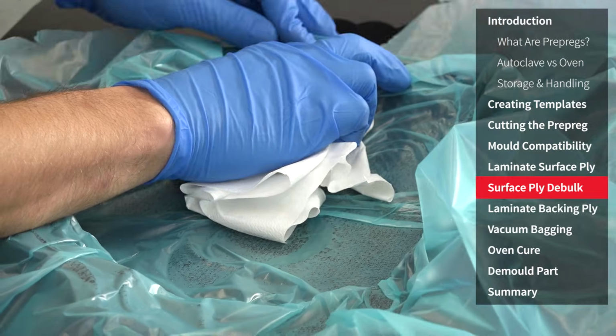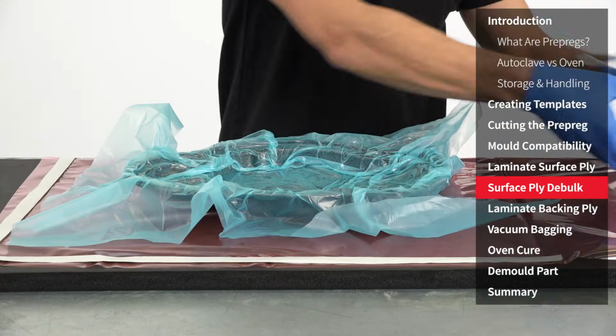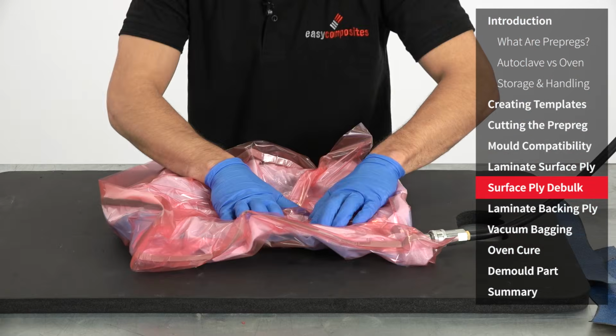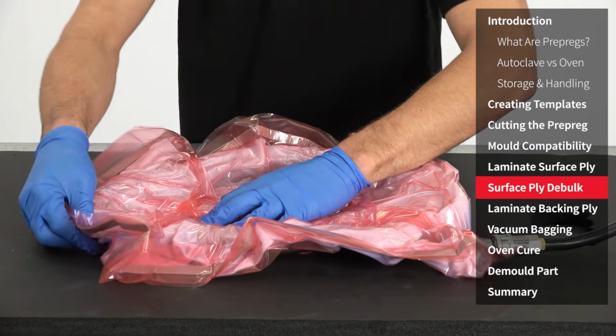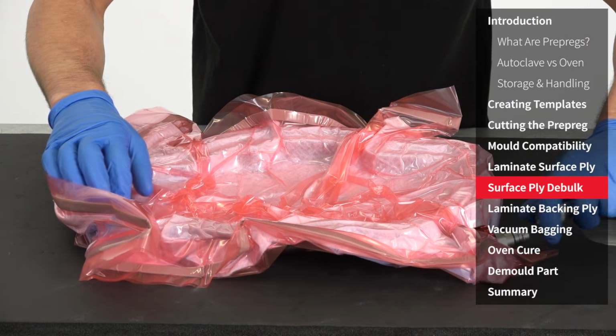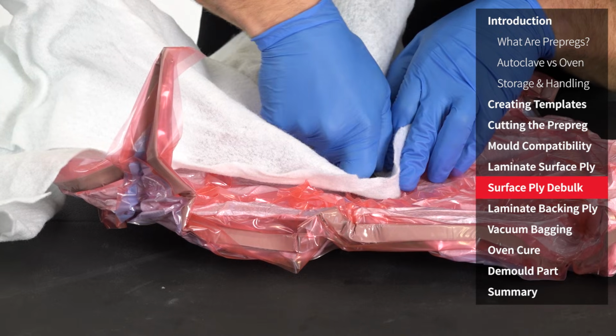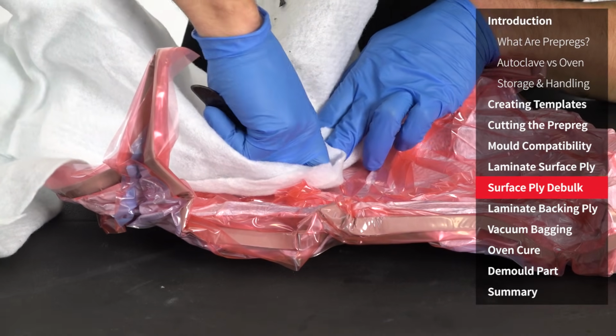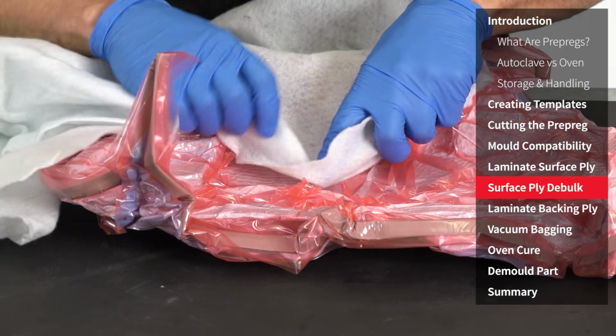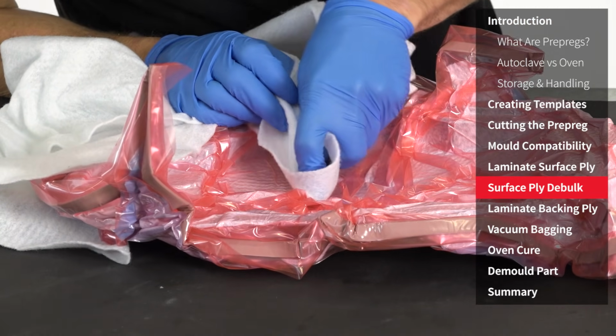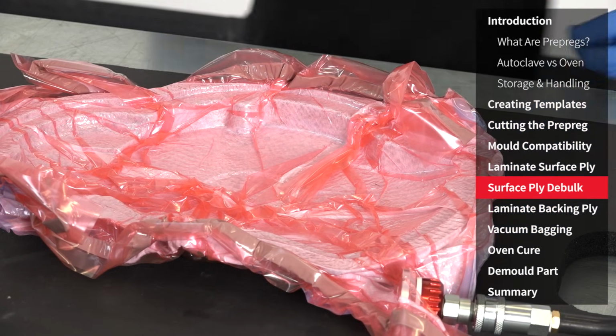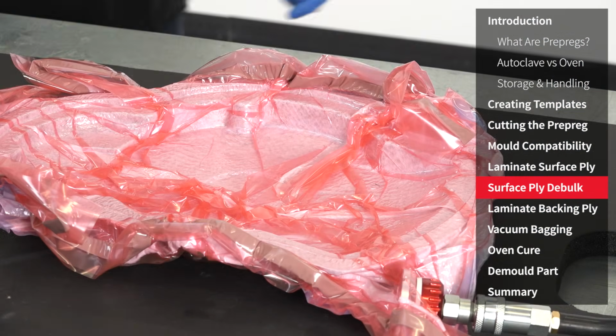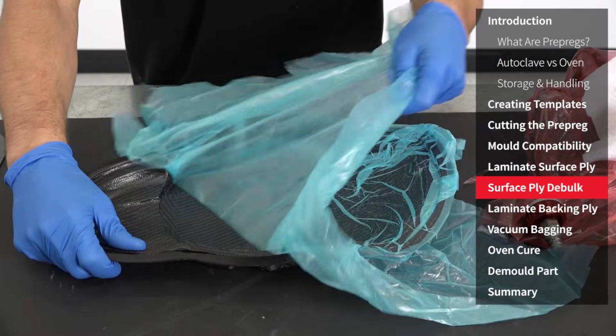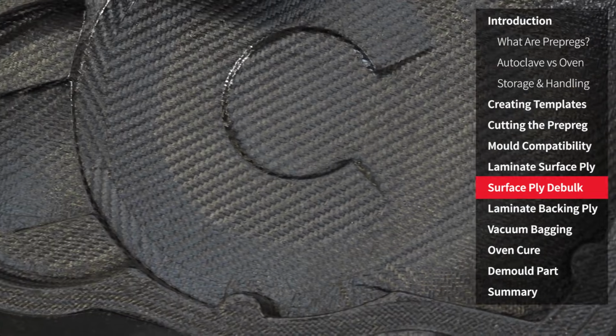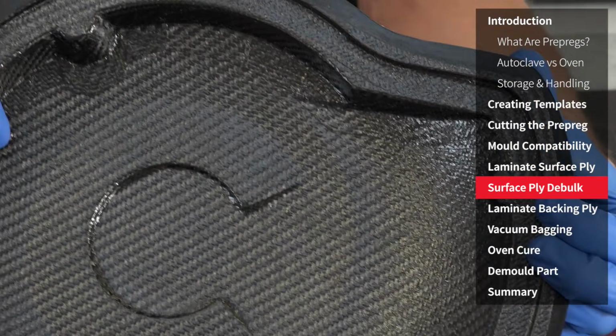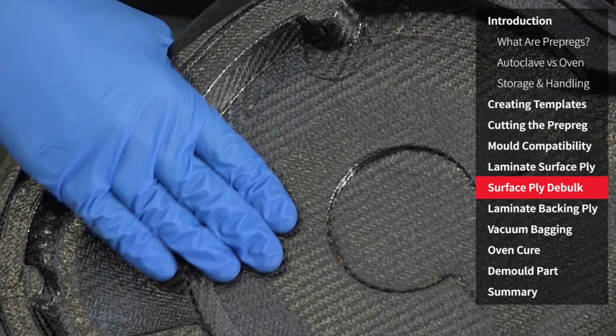Debulking is done using a perforated release film and then a conventional breather and vacuum bag. As with any vacuum bagging process, the bagging should be moved and positioned to ensure that it is properly following the form right into any corners. Using a blunt tool wrapped in breather can help to firmly press it into position. A full vacuum should be pulled on the part and held for at least 10 minutes to ensure all trapped air is evacuated. Once completed, the part can then be removed from the bag ready for the subsequent plies to be laminated. You can clearly see how well consolidated the laminate is after the process.